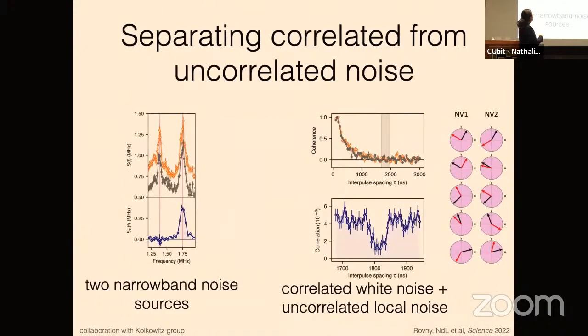And it turns out that we're able to do that pretty easily. So here are 2 NV centers in orange and gray. They each have 2 different peaks when you just do this kind of traditional variance measurement. And one of these peaks is the global signal that we've applied, and the other one is just from local nuclear spins. So in general, these local nuclear spins should not give you a correlated noise signal. And then when we look in the covariance channel, you see that only one of the peaks appears. So it's clear that this is the correlated noise and this is the uncorrelated noise.